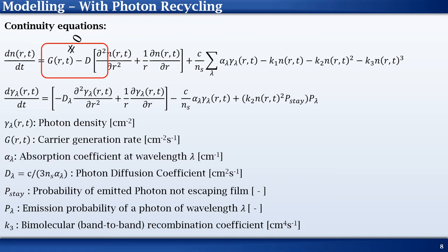Here, we don't set the generation term to 0. Instead, by using a well-defined Gaussian pulse in space and time to model a laser pulse, we avoid the need for underlying assumptions regarding G and N. The second equation is linked to the photon distribution within the film. The first term on the right corresponds to the spreading of photons. The second term relates to photons reabsorbed as carriers. Third, we have the source term for this differential equation corresponding to photons generated from recombining charge carriers.